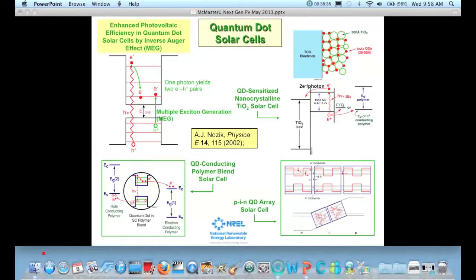So as I mentioned, there are various ways to use these quantum dots in solar cells. One is to use them as a sensitizer, like in a dye-sensitized solar cell, which is sometimes called a Gratzel cell, because he was the first to show this works pretty well. These dye cells have efficiencies of about 10 to 12%, which is closing in on silicon, and it can be very cheap because it's not a high temperature process to make these, as opposed to the first and second generation, where you need to melt the silicon and grow single crystals or produce it from the vapor phase at high temperature. These are low temperature processes, which is one of the advantages of the third generation approach, including the organics. You can do these at low pressure with simple high-speed roll-to-roll processing.